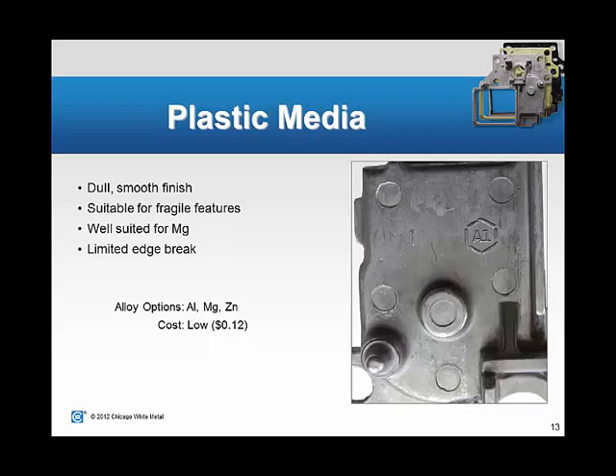The next one we show is plastic media. This is done in the same process, but the media used here is small plastic. The media comes in different sizes and shapes, so you could have balls, cylinders, triangles. It varies depending on the type of finish that you look for. Each type gives a different look. This provides a dull, smooth finish. The plastic media is not very aggressive to the part, so it is suitable for fragile features, as well as magnesium. Magnesium needs to be treated a little more gently, so plastic is good for that.